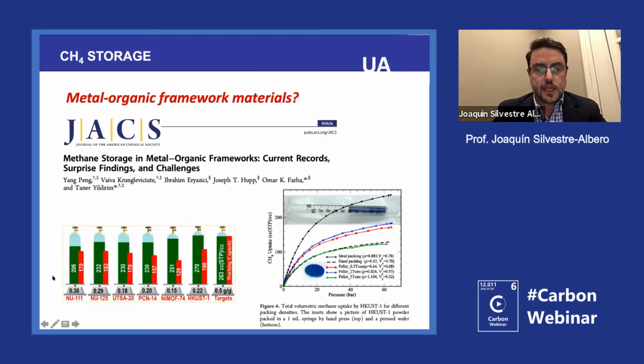In this case, they were just comparing different MOFs. And as you can see here, HKUST-1, which is a copper BTC MOF, is able to reach 270. And you see that the working capacity is very good, 190. So when we saw this paper, it was like, okay, this is very nice because MOF materials can reach the DOE target.